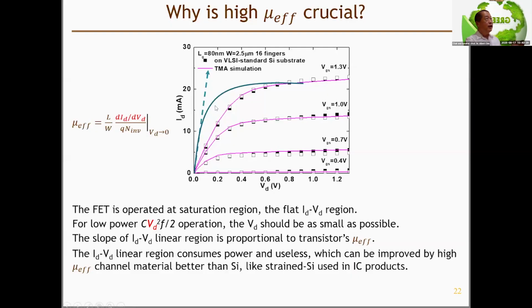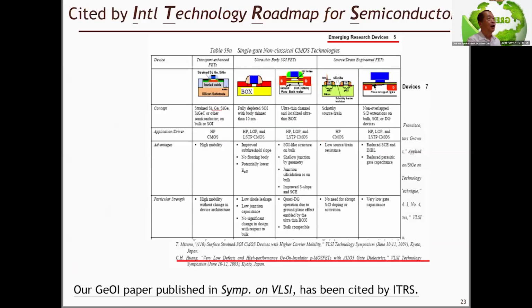The only thing we can do to improve the useless voltage drop in the linear region is to use a high mobility material, because the mobility is proportional to the slope, the ID-VD slope. So in the past, Intel started to use strained silicon for the IC product, and the AMD company right now uses the strained silicon material because it can operate in a lower power consumption region. So that's an idea.